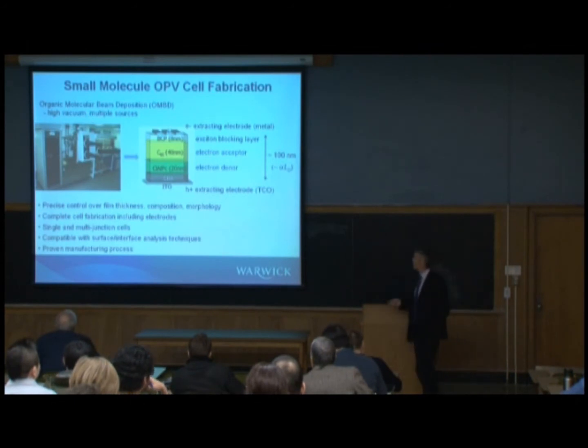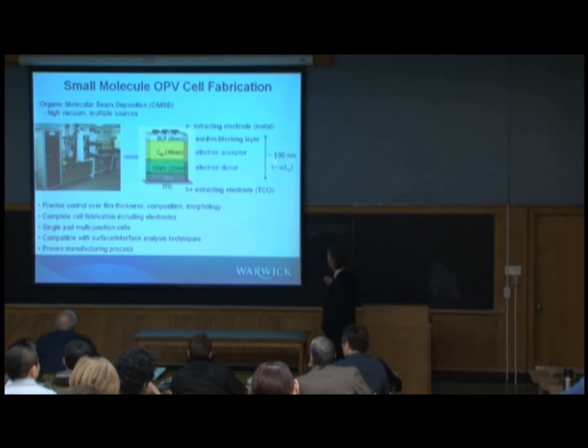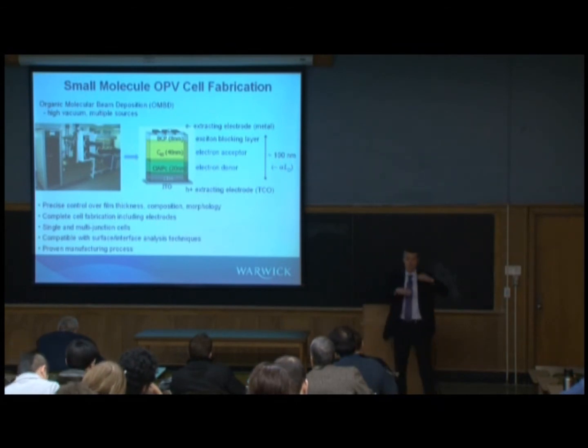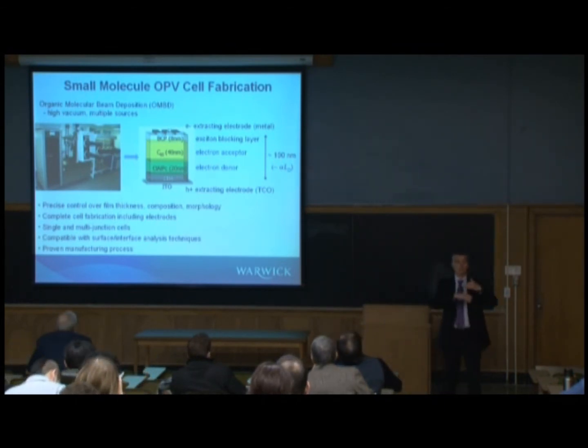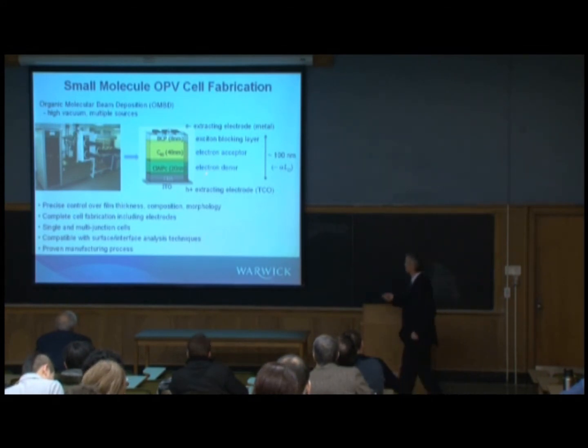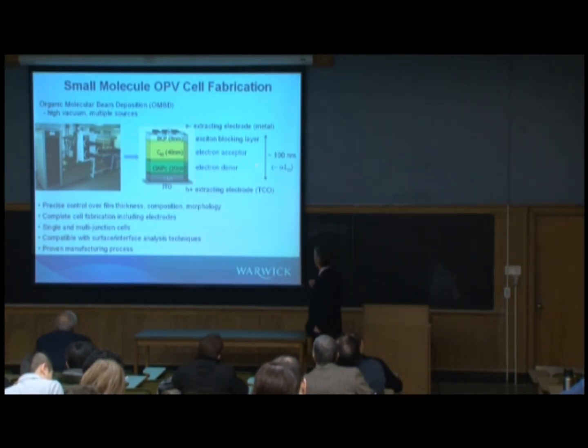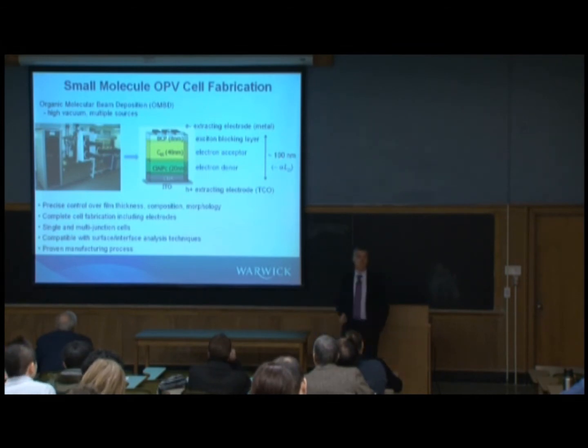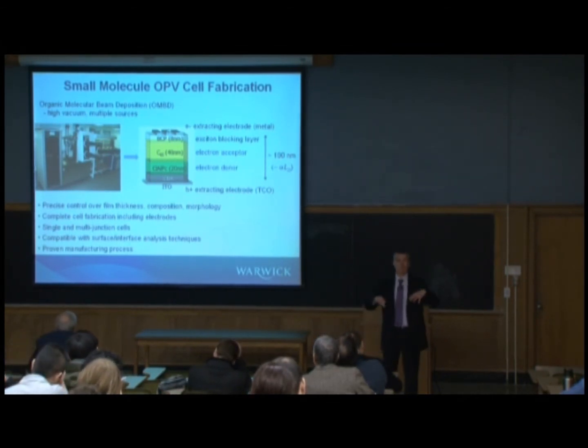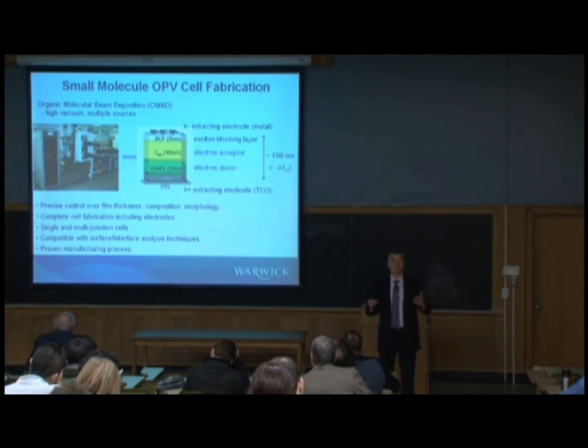So just another aside on this, I said that the thickness of the device is thin. It's constrained by the fact that the exciton diffusion length is low. So these layers can only be a few tens of nanometers. So the total thickness of the active region here will be about 100 nanometers in total. So you're really using very low amounts of material, and these are very lightweight in comparison to some other solar cell technologies.